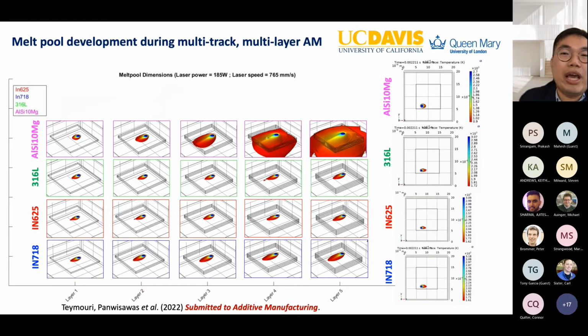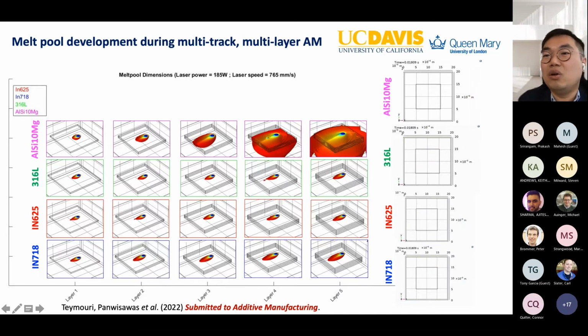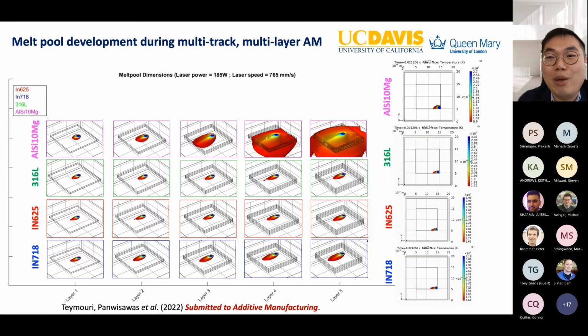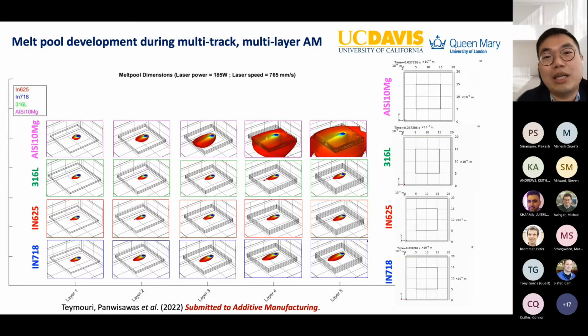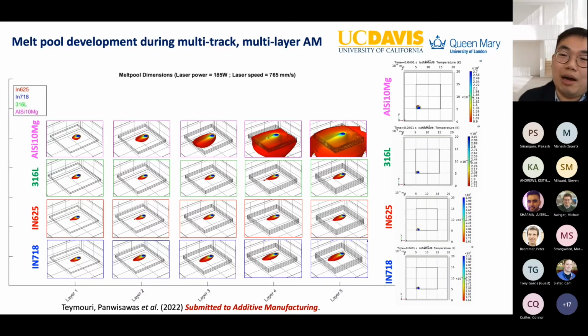And this one, we explore as well the territory of multi-track, multi-layer deposition, where we have fabricated, in this slide, 5 layers. And then you will see that the melt pool develops further and further. There's no steady state melt pool anymore in this process if you do not choose the right window to do so. That's why, if you understand this kind of physics or underlying mechanism, we can optimize the process better for currently available materials like Inconel 625, 316 and aluminum alloy.